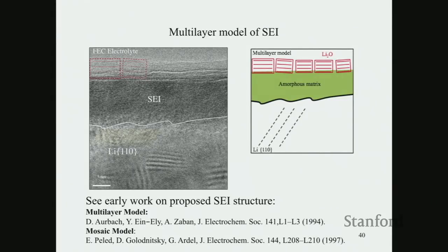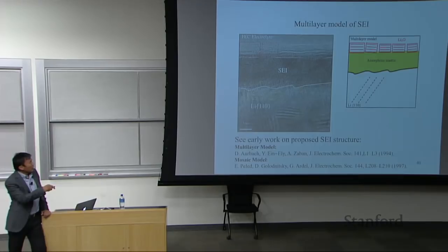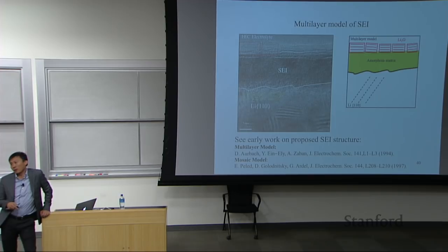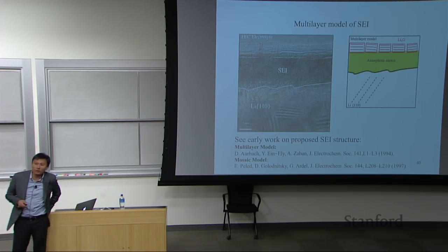And these are two very different structures of solid electrolyte interface. This discovery is indeed different from the initial multi-layer model people proposed. The initial proposal was that the inorganic layer is underneath this amorphous polymer matrix. So we see the opposite. So you say, why is this important?